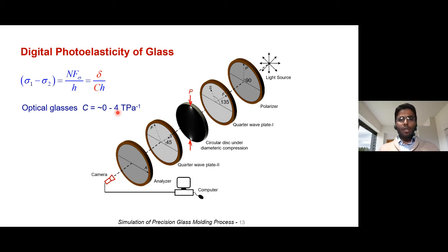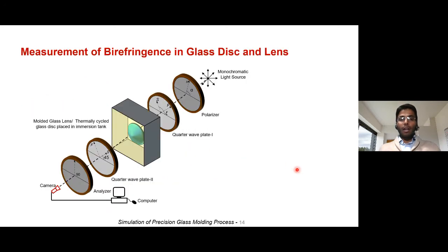And so this we need to measure, for converting stress information to optical information and optical information to stress information. Either way, we need this photoelastic constant. And for measuring the birefringence, we had the experimental setup, where the lens was placed in a matching refractive index liquid, so that the light rays can travel in a straight line. There is no refraction happening.